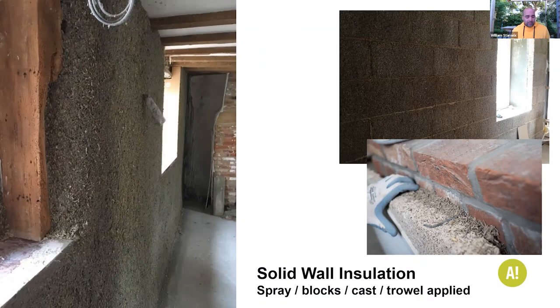So this is solid wall insulation. The picture on the left is the inside of a stone cottage in the Cotswolds. I've sprayed 150 millimeters of hempcrete internally as solid wall insulation. Due to the nature of spraying, it's very easy to maintain the curves and features of the original building. There's no fixings, there's no cold bridges, just a continuous 150 mil layer of insulation, which will then get plastered over. So you can turn a building with not much insulation at all into a very nice, cozy building.